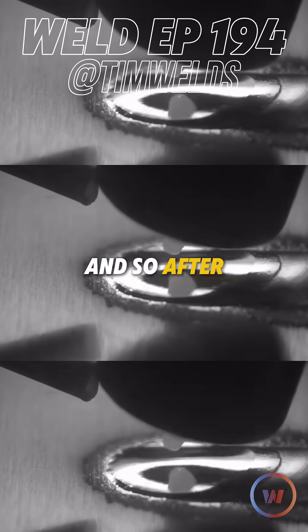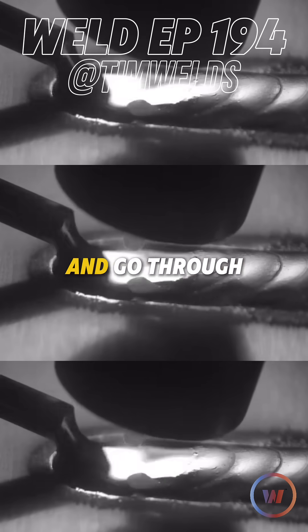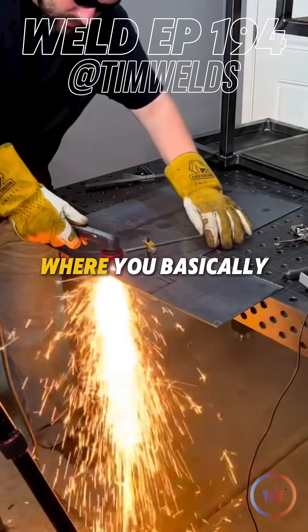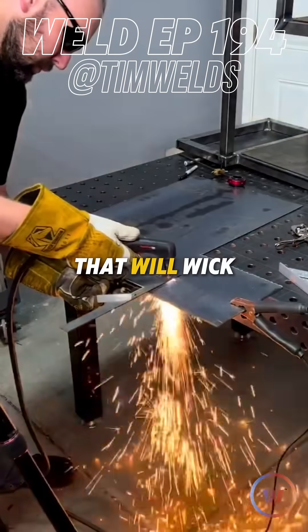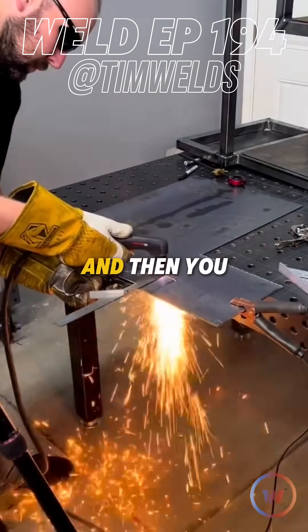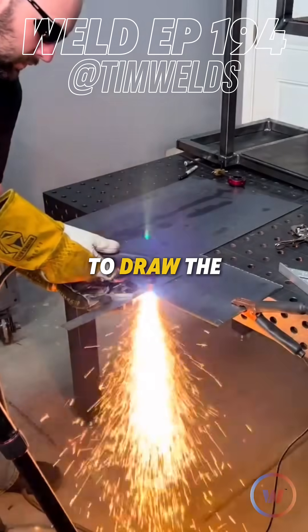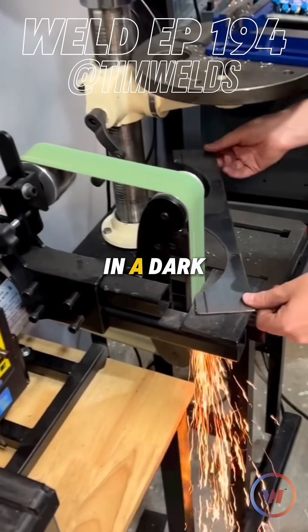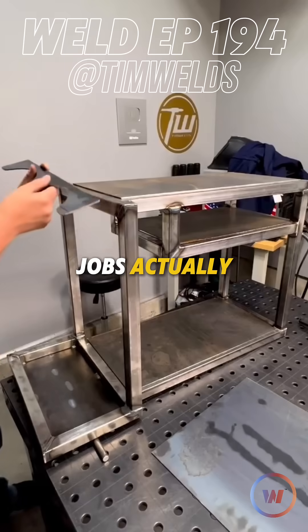After something is welded, the weld will often be covered up, so it'll have to go through a dye penetrant line where you basically soak the part in a fluid that wicks into any cracks. Then you wash the part off and use a developer to draw the dye back out. It's usually done in a dark room with a black light. Those can be really good jobs, actually.